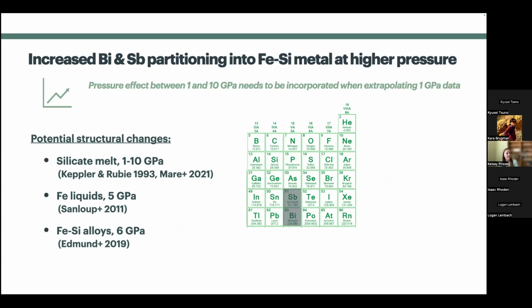In summary, we've studied a range of elements, and of the elements that we studied, we found a pressure effect only for 2 of them. That pressure effect was for bismuth and antimony. That tells us when we're modeling bismuth and antimony at higher pressures, we need to incorporate this change in behavior. As I mentioned, exactly where this change is happening in the 1 to 10 GPa range may be debatable, and the reason for that change is still up for discussion.